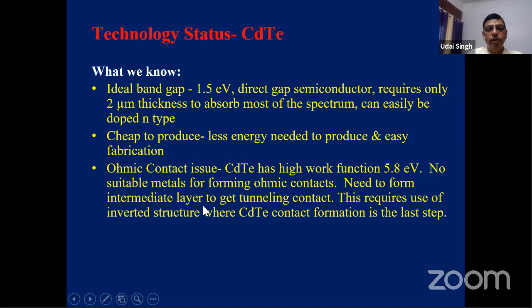So you need to form an intermediate layer to get a tunneling contact. You don't directly deposit metal on the cadmium telluride. You try to have some interlayer in between. So this requires the use of an inverted structure, where CdTe contact formation is the last step.